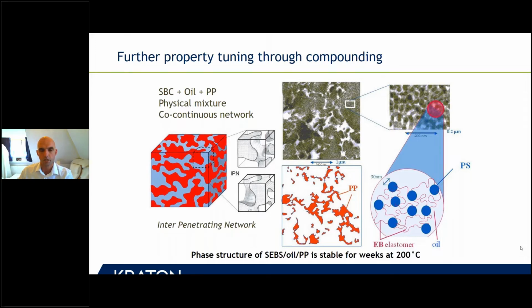There are actually some examples in the US where gel mattresses are being made out of this kind of material, but you can think of anything that looks and feels like a gel. You can make it from this. The nice thing about these phase structures is that if you tune them correctly, they're pretty stable. They're stable for weeks at 200 degrees, once you have them and you don't put them under shear. And here you can see some micrographs, as I showed before as well, some transmission electron microscopy. You can visualize it quite nicely. If you take the right staining method, you can color the styrene domains, and the rest will look lighter.